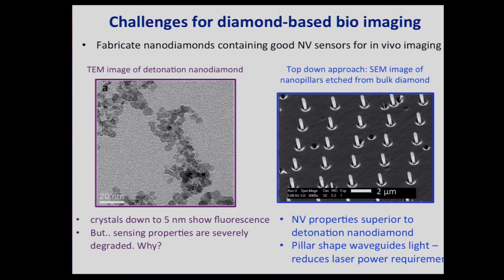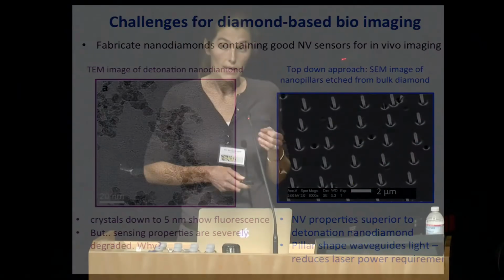But as I mentioned, the sensing properties are severely degraded. Again, the question is why. It's an interesting question, and it's not known. Another approach that we're taking in the lab is starting with a really clean piece of diamond that we've grown and doing top-down fabrication, so actually etching nanoparticles. In this case, we're etching nanopillars. This is an SEM, a scanning electron microscope image, of an army of little nanopillars of about 200 nanometer diameter, and they're a few microns tall. One can make these smaller. This is our first demonstration. And we've shown that NV properties in these are superior to those in nanodiamonds. Another nice benefit is that these pillars act to waveguide the fluorescence out of the pillar, and therefore increase our collection efficiency significantly.